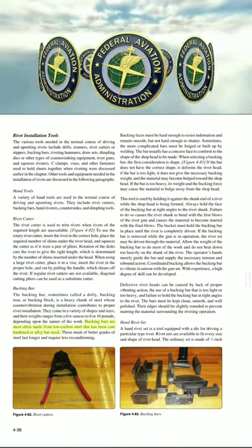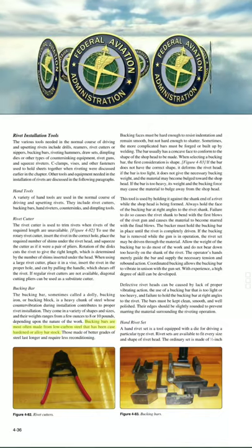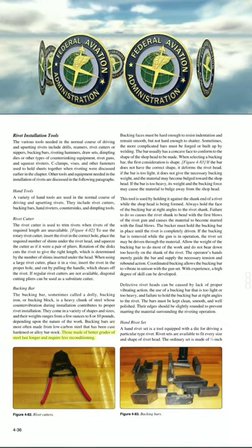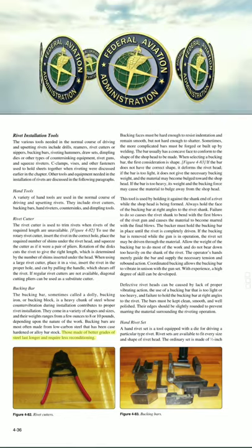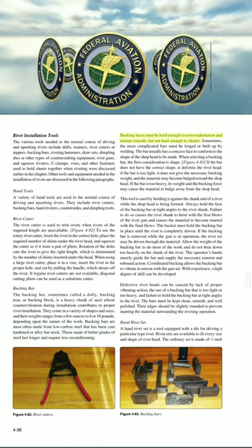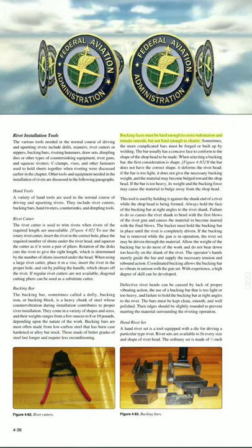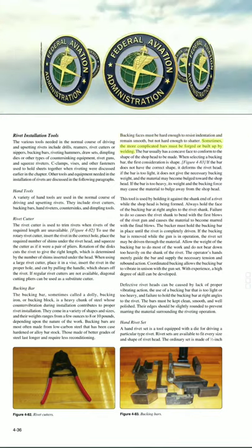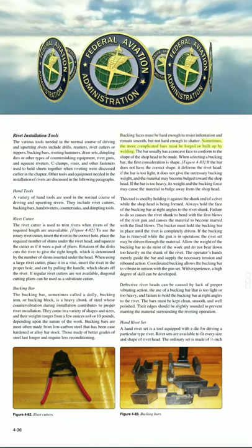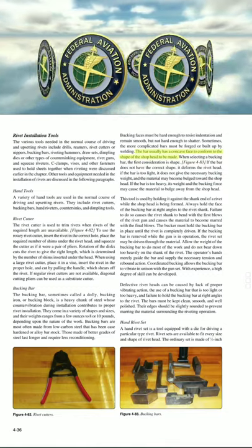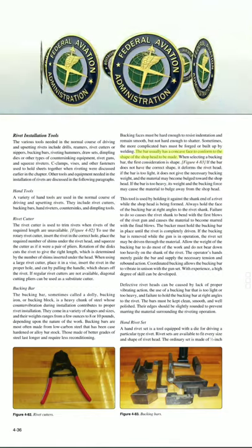Bucking bars are most often made from low carbon steel that has been case hardened or alloy bar stock. Those made of better grades of steel last longer and require less reconditioning. Bucking faces must be hard enough to resist indentation and remain smooth, but not hard enough to shatter. Sometimes, the more complicated bars must be forged or built up by welding. The bar usually has a concave face to conform to the shape of the shop head to be made.